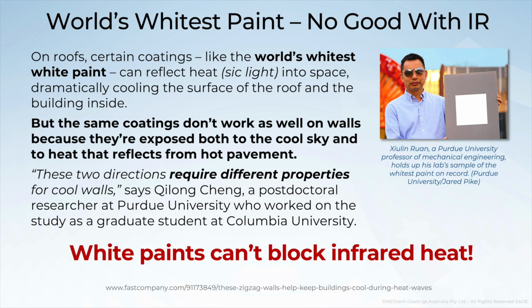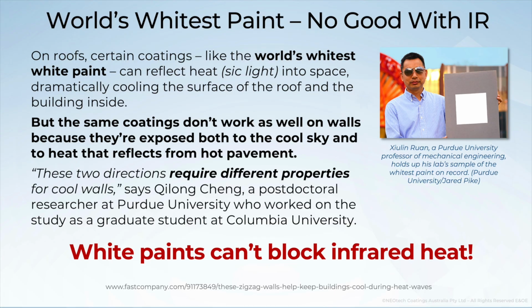As an example of the solar reflective index, Purdue University recently put out what they claim was the world's whitest white paint, which actually reflects light, not heat, as we've explained. However, what they also inadvertently declared was the fact that the coating doesn't work very well on walls, because it can't stop the infrared heat from the hot pavement, so they have to use a different product for that. That 100% clearly explains that they rely just on reflection, making it as white as possible to reflect the light, but they are unable to stop the infrared heat, which is exactly what these coatings should be doing. To stabilise a substrate, you must stop the heat.